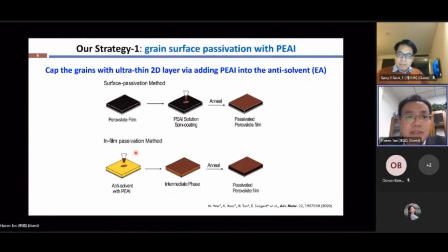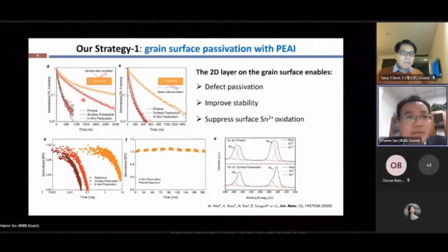So what we did is different. We added these long-chain ammonium ligands in the anti-solvent so that we can get 2D perovskite materials not only on top of the film surface, and we think that this 2D layer can also form at the grain boundaries, so that it will have better passivation. We proved our idea through the PL decay measurement. We found that using this, we call it in-film passivation, we can get a longer carrier diffusion length, not only on the top surface, but also at the bottom surfaces.